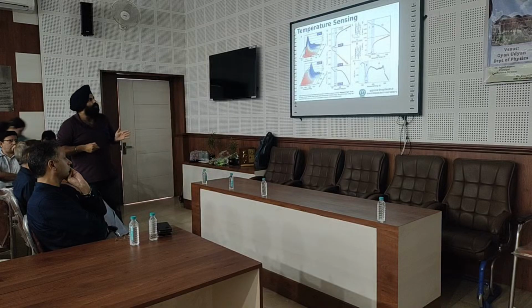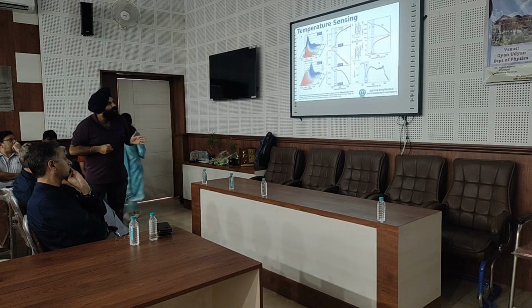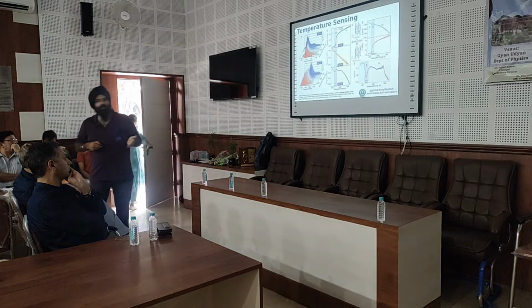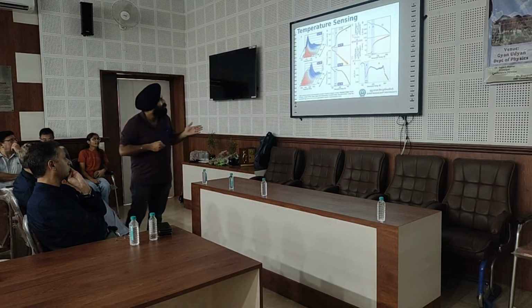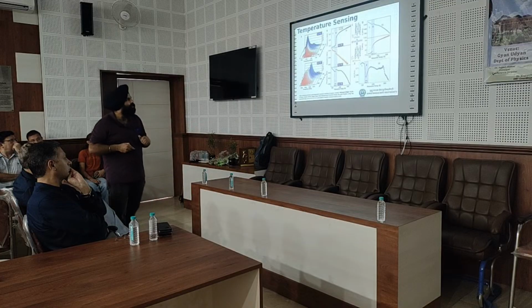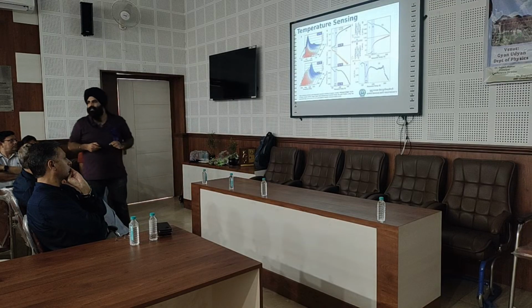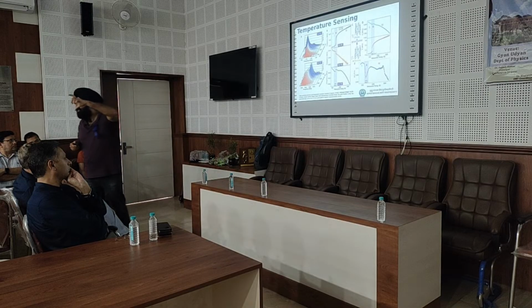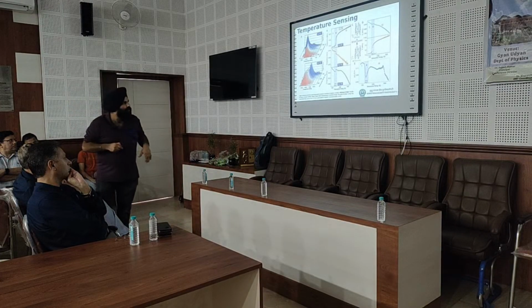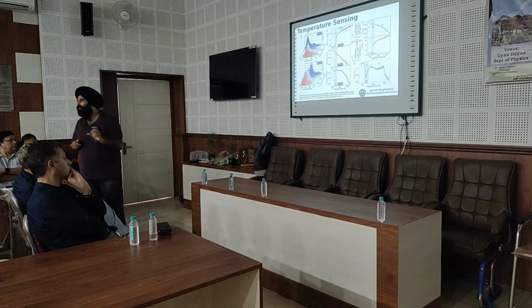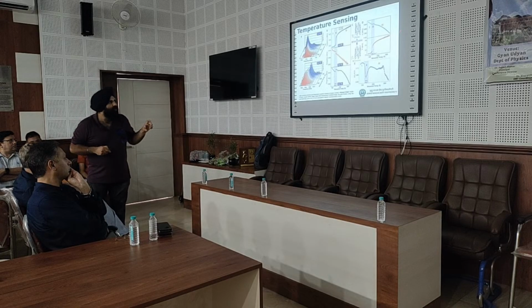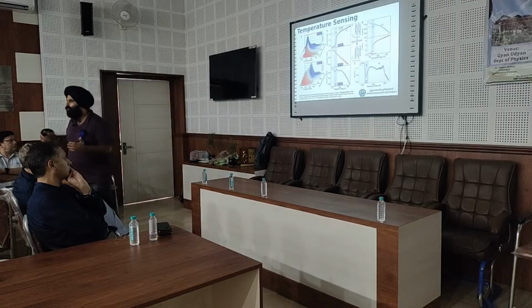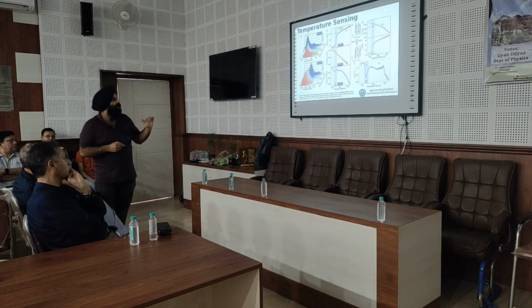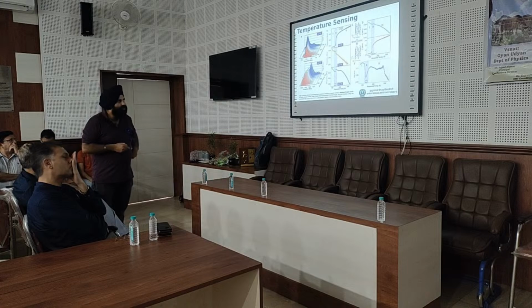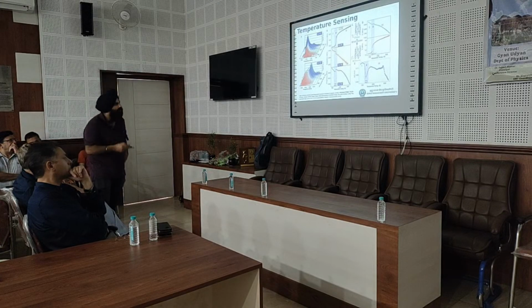Also at one particular temperature, at 193 Kelvin, we see a phase change. This organic crystal changes phase from triclinic to monoclinic. Whenever there is a phase change, the system becomes really sensitive, so this particular regime has a very high sensitivity. In principle, we can make a sensor by exploiting the phase change property, and this sensitivity will be huge. So this is a material which actually shows a phase transition also, and that's why it is very important.